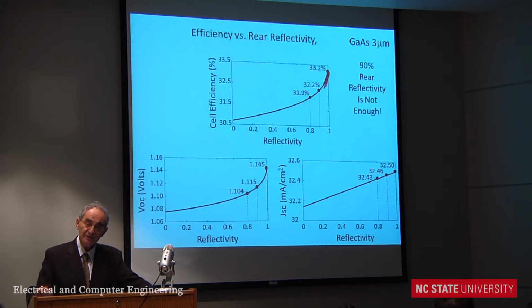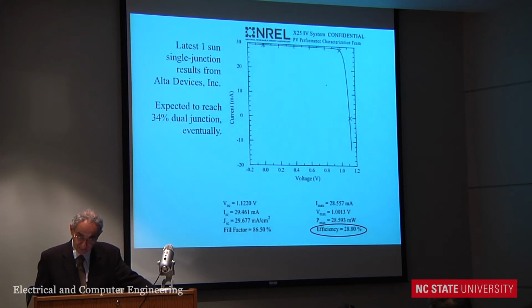So that's where your rate of improvement is the greatest. So 90% is not really enough. And same with the internal luminescence efficiency. Again, 90 is not enough. You want close to 99 if you can. So that's part of the secret.